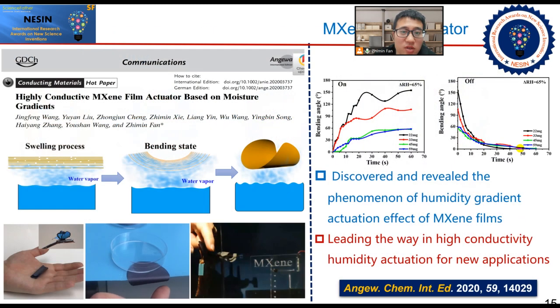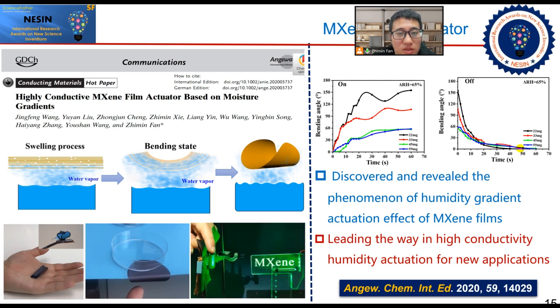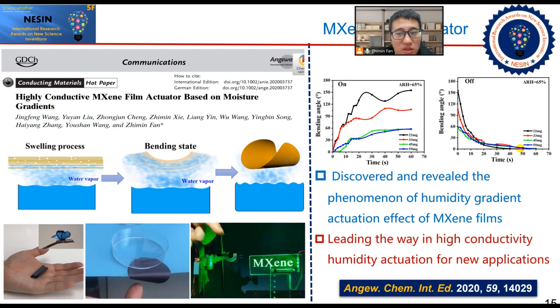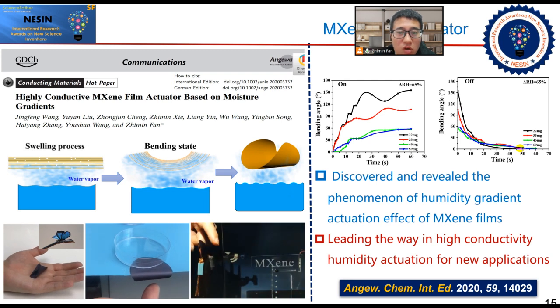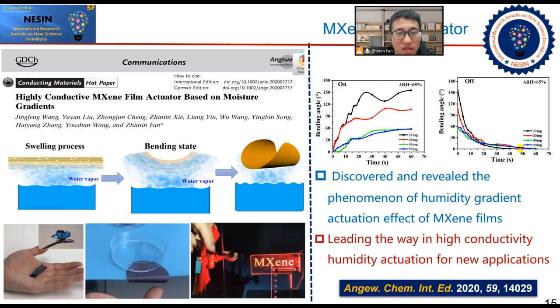For this series of problems, after a long exploration, we have published the solutions in journals such as Angewandte and ACS Materials. It has long been believed that MXene films cannot be moisture actuated because of the low oxygen content and high stiffness of MXene terminals.